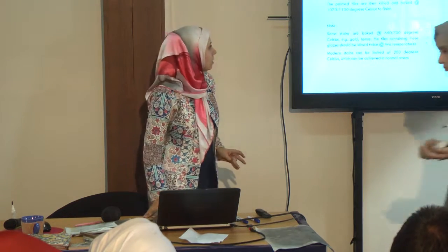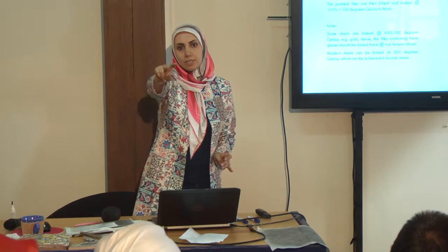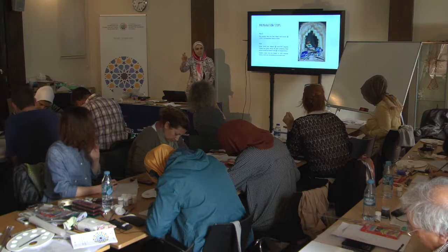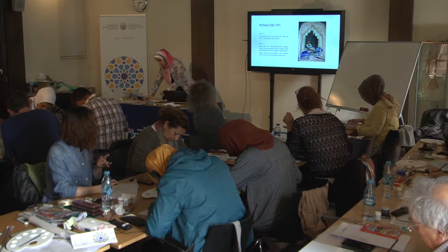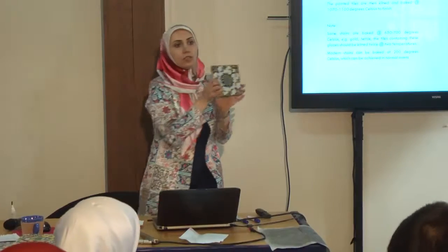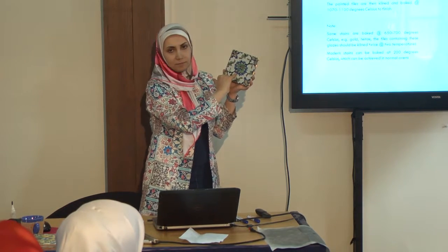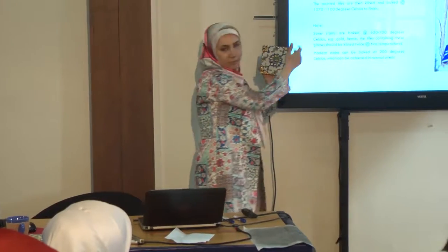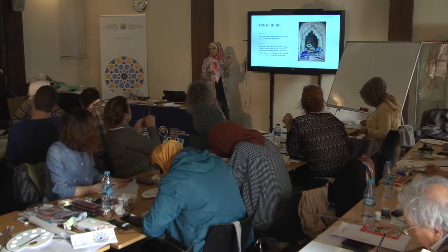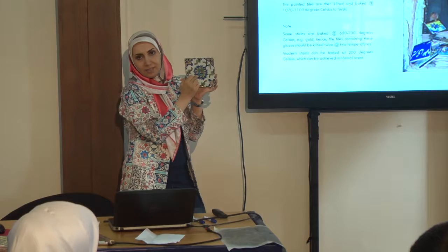The traditional stains and glazes are baked at 1070 to 1100 degrees Celsius. But the inks that we just gave you are modern stains that can be baked in a simple oven, 200 degrees. Sometimes you use, for example, gold color, like this one, in your tiles. The temperature is different from other stains. All the other colors bake at 1100 something, but this one only at 650, 700. If you paint it all together and put it in the kiln, these will burn.